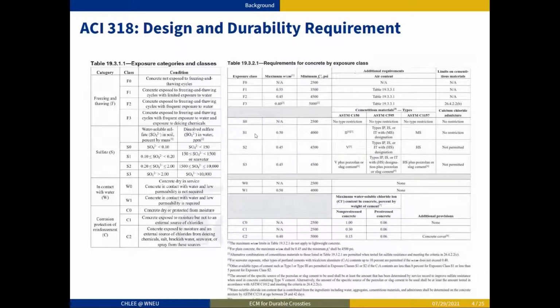Also, if you take a look at the table on the right-hand side, according to the different exposure conditions, they just provided us the maximum water cement ratio and the minimum strength condition. Therefore, any mixtures satisfying both maximum water cement ratio and minimum strength conditions will satisfy particular durability conditions.